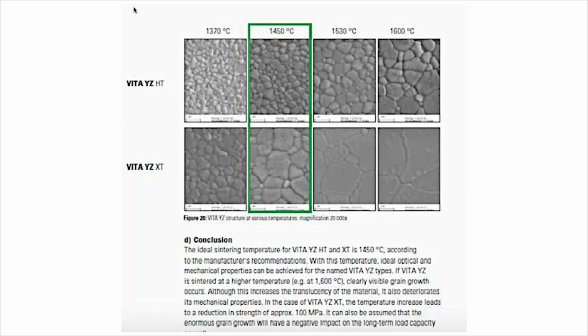These are the crystal sizes of the material. So if you fire it too high, especially on a 5Y material, you can increase the translucency for sure, but you're going to weaken it. So if a little piece chunks off on a 3Y, you're hardly going to see anything. If you chunk off something on a 5Y, you're going to notice big time, because the size of the grains, the boundaries, are much larger.